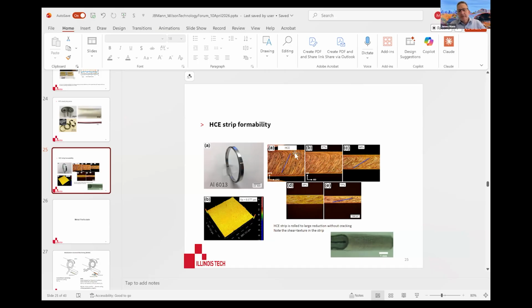But these are strip. This is showing what happens when we roll that strip. And you can see that the orientation of the shear flow begins to go in the longitudinal direction. That's just the result of rolling. So pictures B, C, D, and E are taking that strip and rolling it through subsequent rolling steps. But rolling has the characteristic orientation that's always in the rolling direction. That's actually a limitation of the rolling process as well. It does not have the ability to actually control orientations in the way that HCE does.